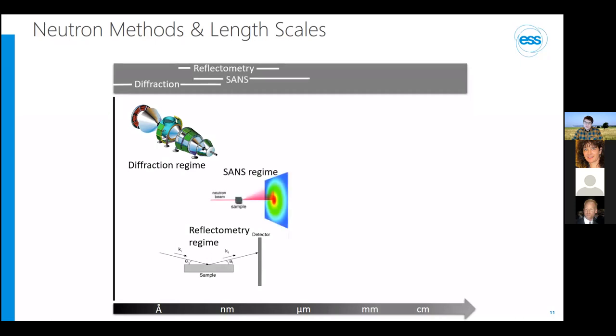In one of the last seminars, my colleague Andrew Jackson already explained a little bit about small angle neutron scattering, which can be used to study all sorts of substances on similar length scales as reflectometry, between 1 nanometer and up to a few hundred nanometers. The length scale can further be extended towards a micrometer range by using very small and ultra-small angle neutron scattering.